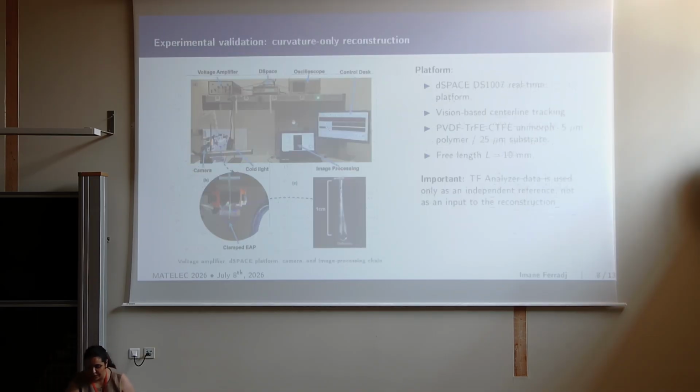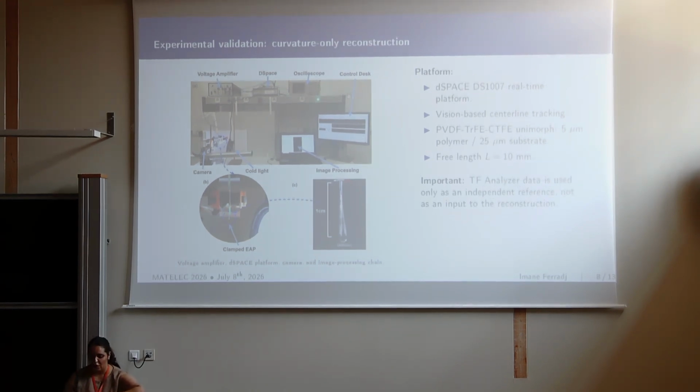What we do is we track the curvature through image processing, and at the same time, we only look at the curvature at the tip of the actuator. So we use the pure relaxor here with an active thickness of 5 micrometers and 25 micrometers of substrate.